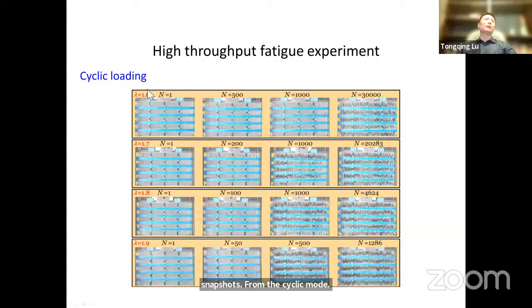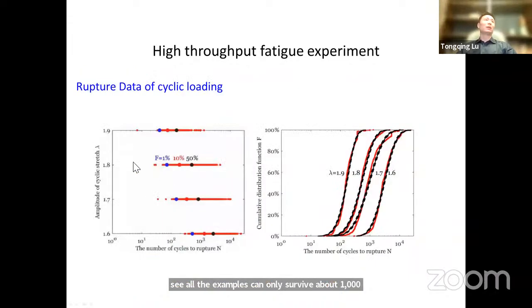For example, at a given stretch amplitude of 1.6, you can see that as the cycles increase, more and more samples rupture. At another stretch amplitude, for example 1.9, all the samples survive only about 1,000 cycles. So we can collect all the fatigue data.